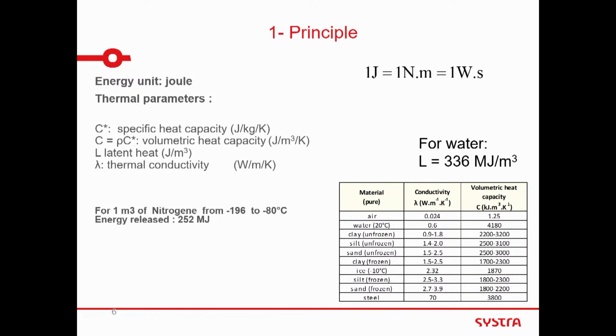Another figure to compare is the energy of nitrogen, N2. So, two ways of putting cold. Either you use a mix of water and salt, okay, which is called brine, or you can use nitrogen. There are advantages on both techniques, we'll see later. 1 cubic meter of nitrogen, nitrogen is liquid under minus 196 degrees and goes to gas to minus 80. So when it passes from minus 196 to minus 80, the energy released is 250 megajoule.